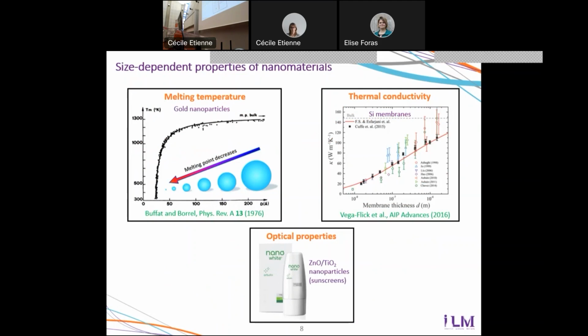Another example here, not on nanoparticles, but on very thin membranes made of silicon. The thermal conductivity of these membranes is not the bulk one, which is this line here. It's lower and it's decreasing with the thickness of the membrane. So these are two examples of size-dependent properties of nanometric objects.